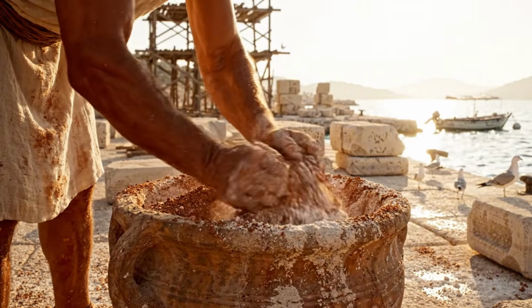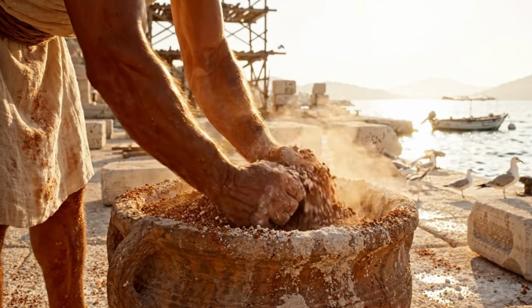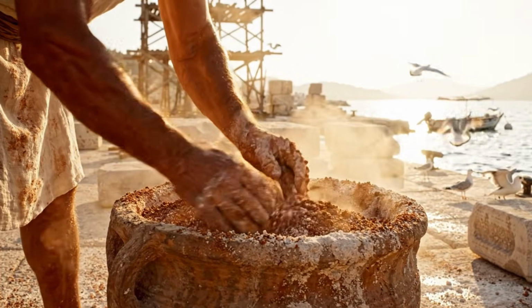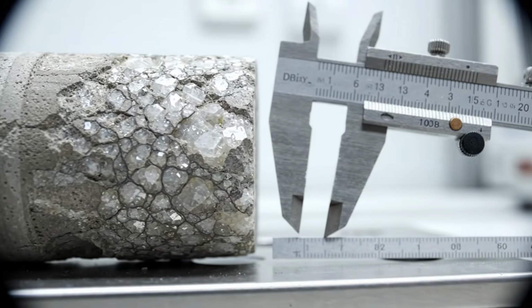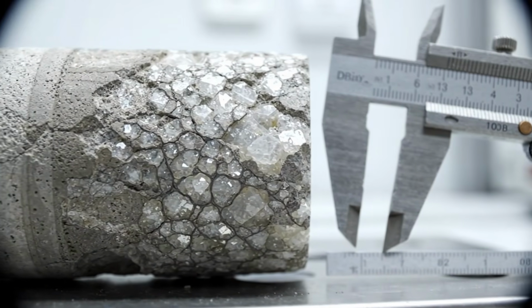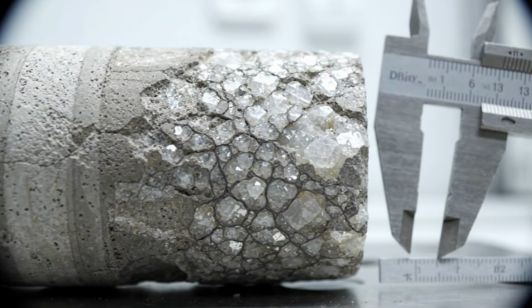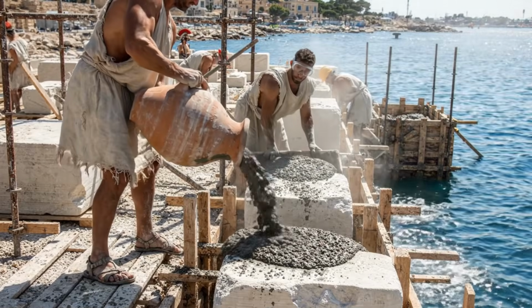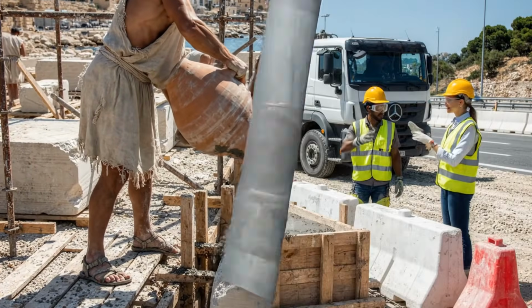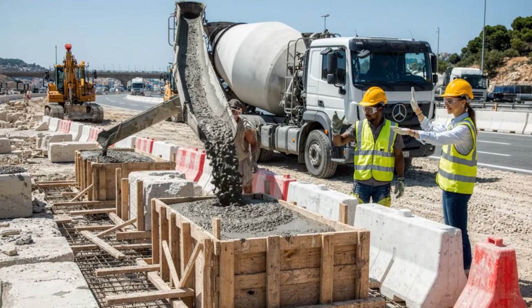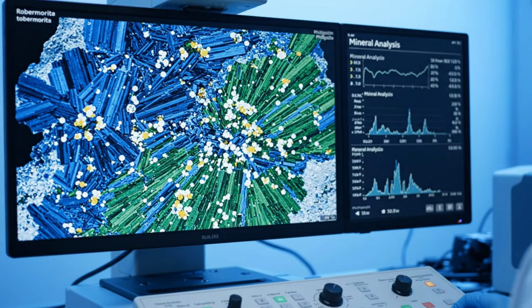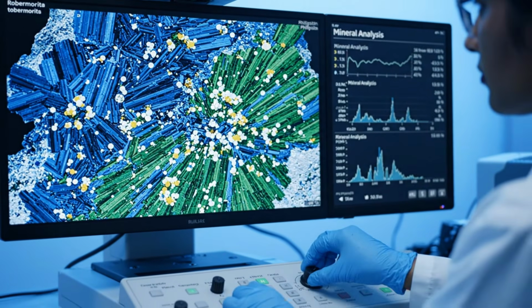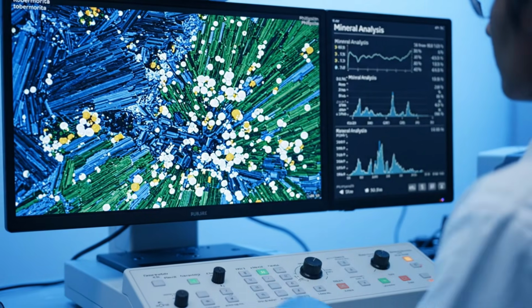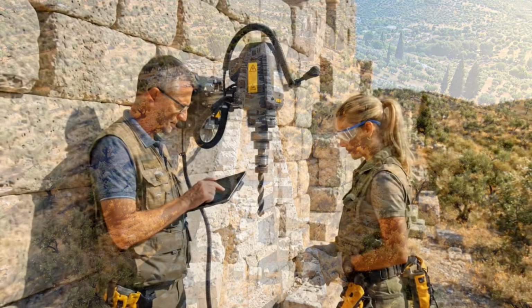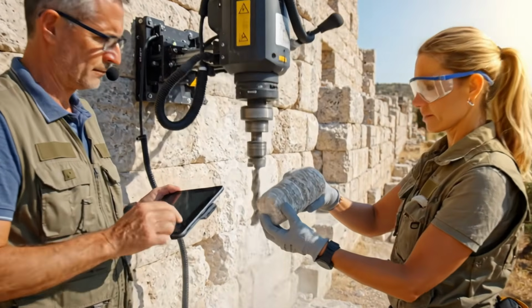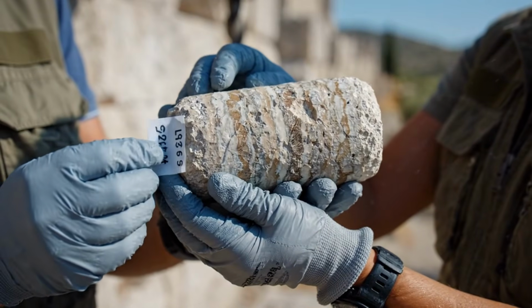Nobody had looked for virtue in the specks, because nobody looks for virtues in what they have already classified as a flaw. So stack the three mechanisms, and the title of this story pays out. 1. The binder, lime plus volcanic ash, reacts with seawater over centuries to grow interlocking crystals that reinforce the matrix and lock up the very ions that destroy modern concrete. 2. Hot mixing seeds the material with reactive lime clasts that self-seal small cracks, around 0.5 millimeter, the everyday cracks that let corrosion in. And they do it in weeks, not centuries.